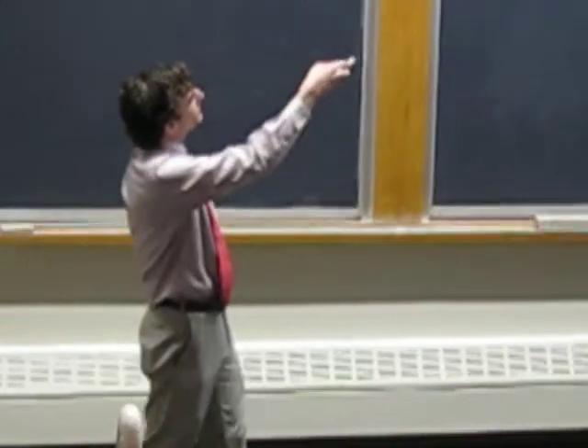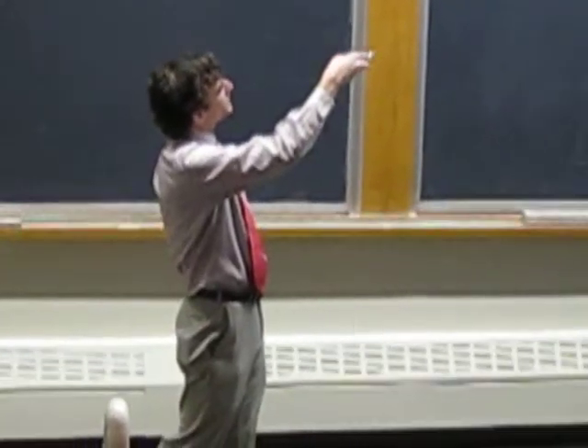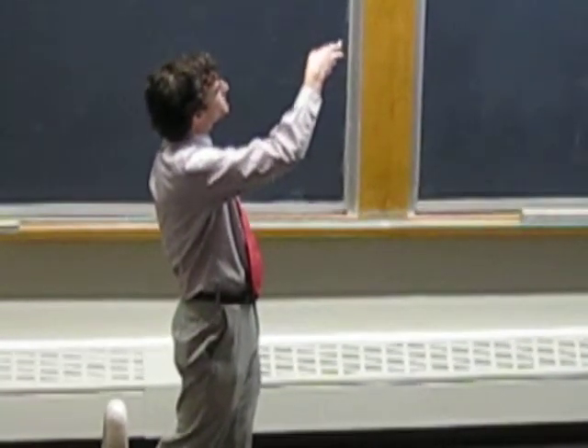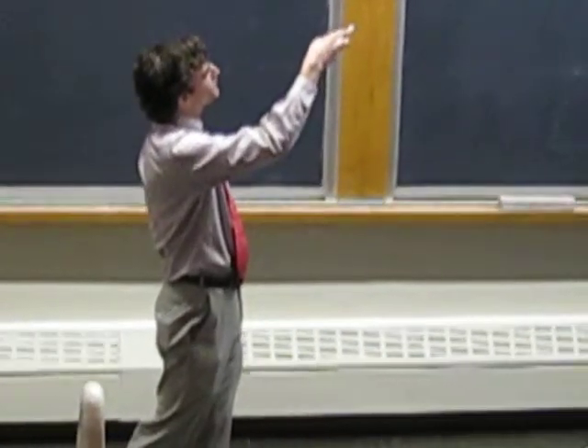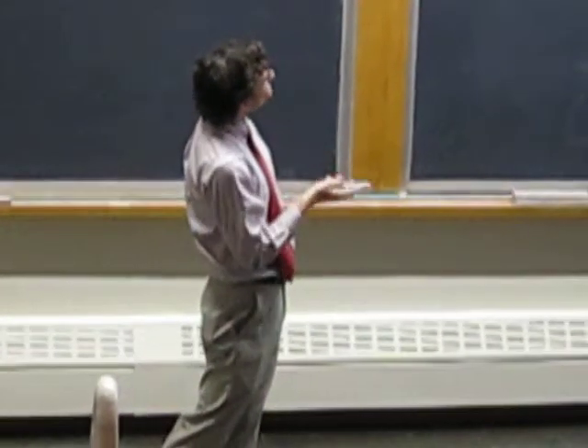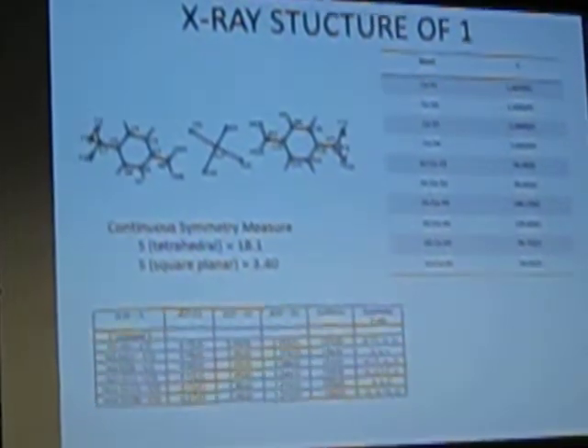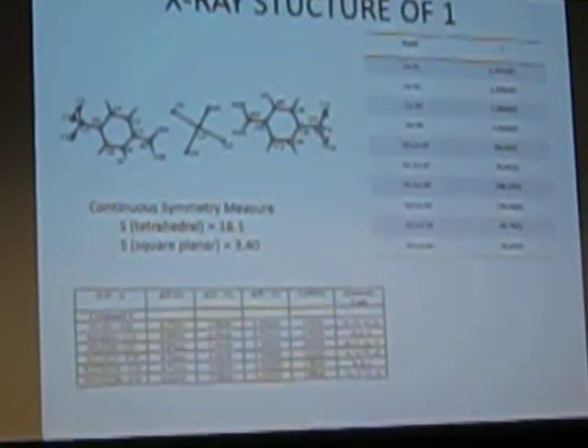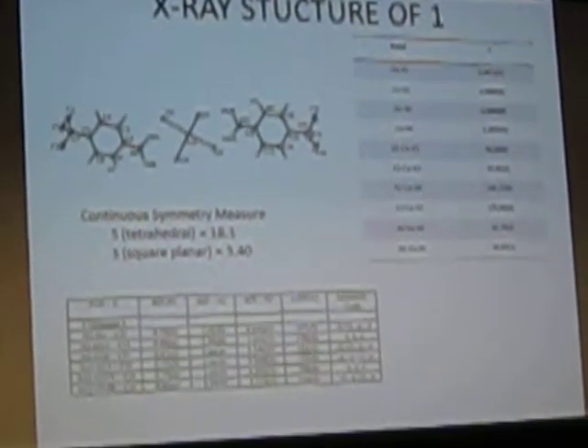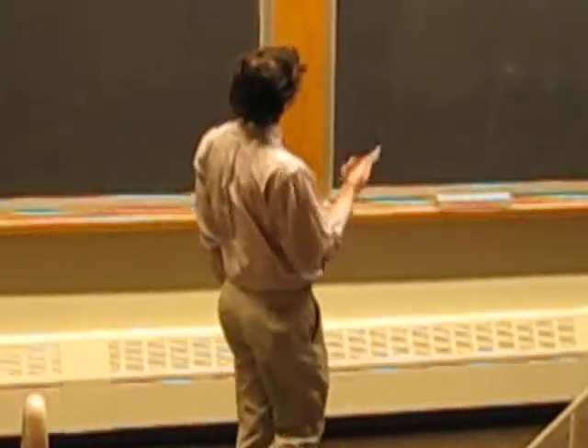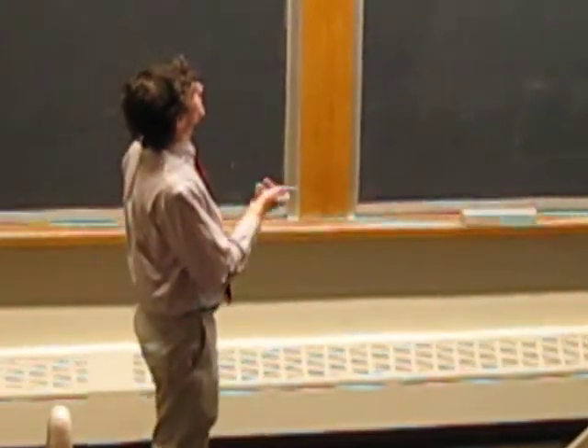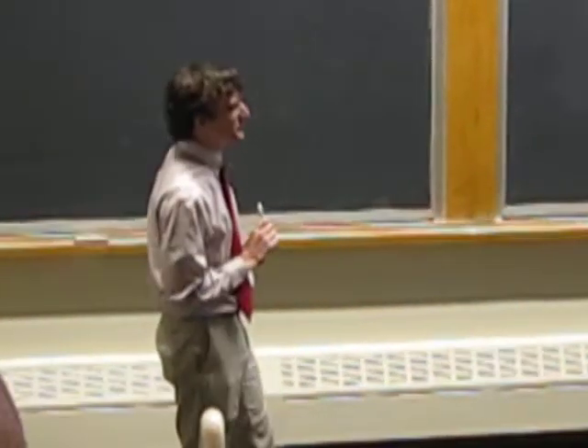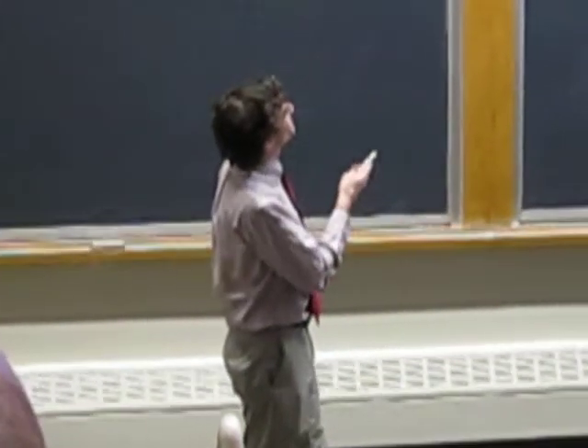This is just the IR of the final material with a close focus on the NH bend of the pyridinium ring. So we have indeed protonated this ring. And the CHN data agrees with the composition of the final product, which is good. So then the X-ray single crystal diffraction data, which we collected over in New Zealand, Dr. Jan with Rockire collected the data for us, and then I personally solved the crystal structure with help from Professor Turnbull. And so this is the picture that we get.